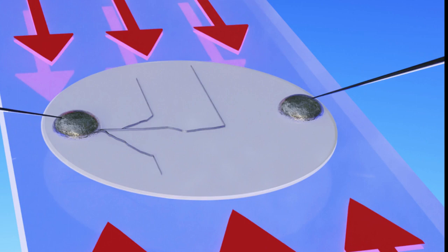The solution to the problem turns out to be more stress applied in just the right direction and with the right amount of force. While previously, some researchers thought that dendrites formed by a purely electrochemical process, rather than a mechanical one, the team's experiments demonstrate that it is mechanical stresses that cause the problem.